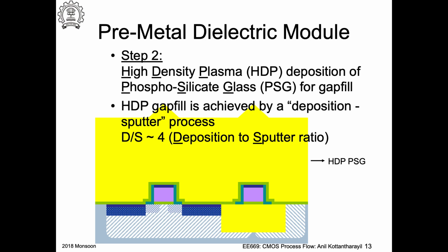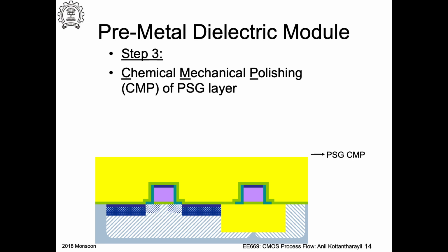One thing that you may note here is that wherever you have the polysilicon gate, you have a triangular shaped top in the cross section. That is coming from what we have discussed already. This is a consequence of the etch and deposition process. You are depositing, but also introducing a little bit of sputter etching, so that creates this triangular shape. If you want to review this, you can go back to the sputter deposition, or even the PECVD process description in a previous module.